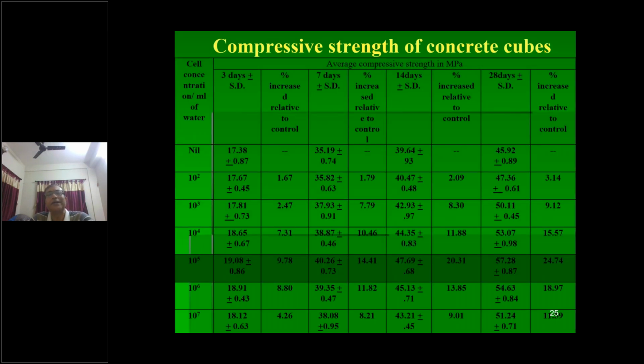Now, after mortar, we started with concrete. In the same manner, a more elaborate study has been made, starting from 10 to the power 2 to 10 to the power 7, and at 3 days, 7 days, 14 days, and 28 days. Here we have used only the 72 degree temperature microorganisms. In these cases at 10 to the power 5, we are also getting an improvement in strength of 20 to 25% at different ages.